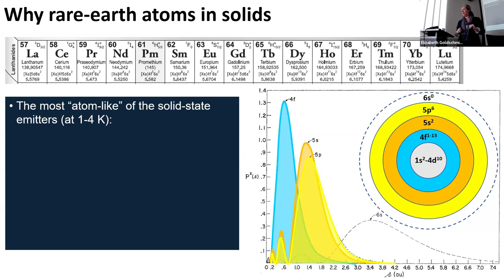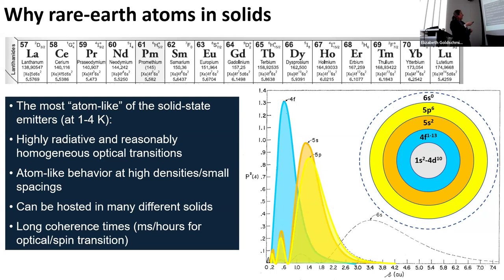So basically what we get are these highly radiative transitions and reasonably homogeneous. So the atom-to-atom shift in energy is relatively small on an absolute scale. The energy comes back out in light. It couples only weakly to phonons and other things in the lattice. I can put them really close together, which is going to become important in a few minutes in the talk. And they don't even really see each other. How much is the inhomogeneous problem? We're going to talk about that in a second.